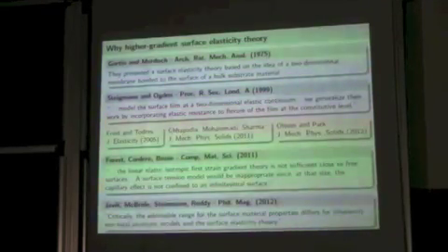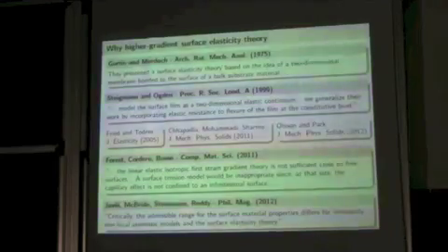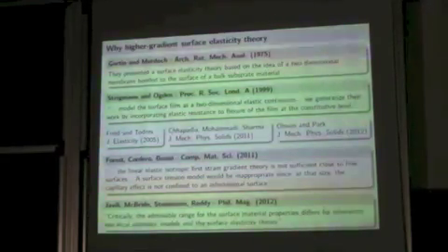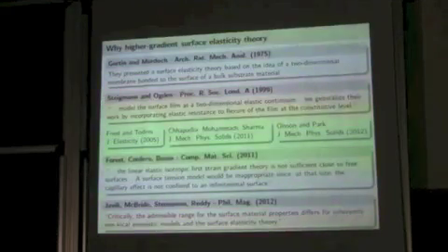At the end, we have also this additional thing. What we did, and I think we also saw it in the talk by Victor Eremeyev, is look at the surface elastic parameters, you can basically calculate the admissible range for these parameters, and you realize that the admissible range is not capable of capturing that weakening effect.